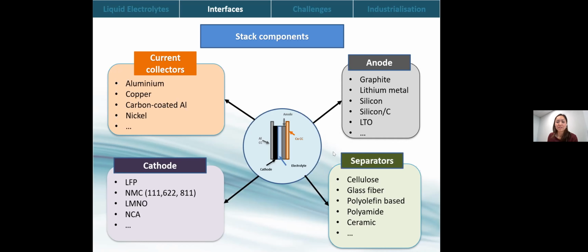The other challenge is the interface between separators and electrolytes, and sometimes even between cathode and separators with electrolytes, it just doesn't match. So here we have to look at the affinity of different materials with the electrolytes. Basically with cellulose and fiber, there's not much of a problem. But when it comes to ionic liquids, polyolefin-based separators can be a challenge to wet. We also have other separators that work well.